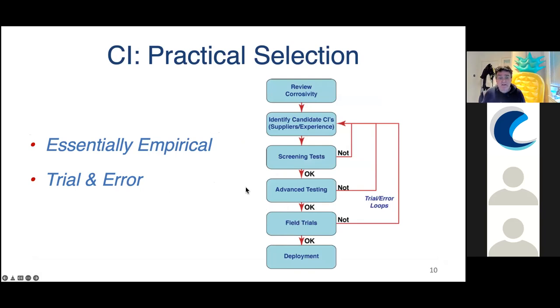So what about practical selection of inhibitors? Well, that's shown on the right-hand side. What is typically done by many people in the industry in engineering scenarios is that the corrosivity is reviewed, and then potential candidate inhibitors are selected based either on the user's experience or supplier's knowledge. On that basis, a number are selected, then a series of tests are done, some basic screening tests. And then for the ones that are better performing, there'll be advanced testing to make sure they're functioning, and then on to field trials and then to deploy if everything is okay. And if they're not, there are these series of loops to go round and repeat.